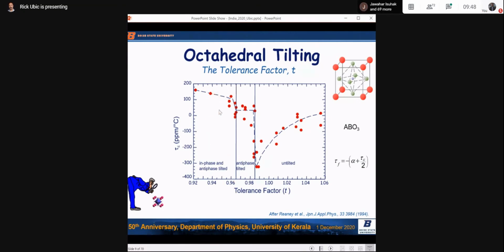Now, there are some exceptions to this, and it's not an absolute rule, but it's a good rule of thumb. And it's definitely the case that as the tolerance factor goes down, the degree of tilting increases. So you get much more heavily tilted structures down here than you would over here. Okay, so these are our properties, right?